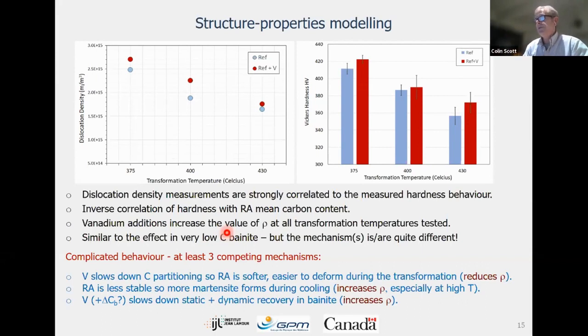The vanadium in solid solution, plus possibly an increment of bainitic carbon, slows down the static and dynamic recovery in bainite, and that's going to increase the dislocation density. And the balance of all those three effects, and possibly other ones, is what determines the relative increase in strength when you have vanadium additions.